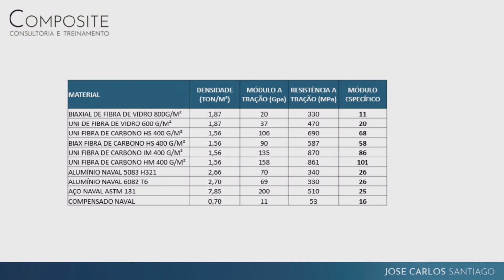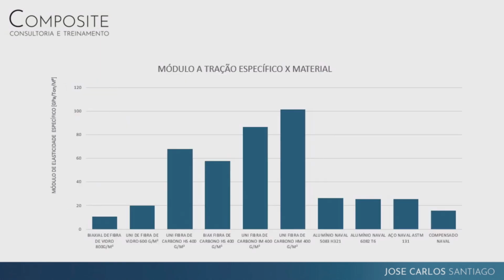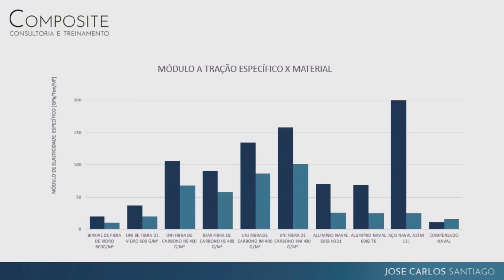When we take all those values and divide by the density of the material, we see that all that relationship that we had, that steel was way above the others, it starts being under carbon fiber. So you see it better when we have one chart next to the other. In dark blue, that's the elasticity modulus alone for each material. In light blue, the specific modulus. In steel, it had a very high amount. And when we compare this amount to the density of the material, we see that it drops a great deal. That's why this material is so used in these vessels that require more speed and strength.